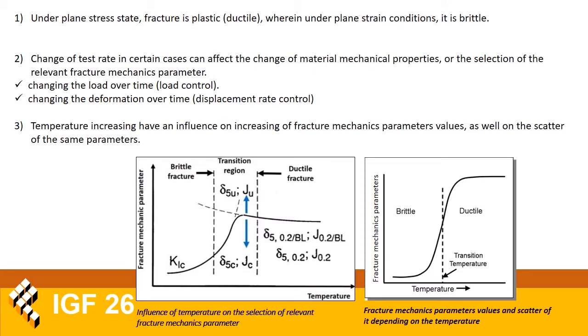As it is well known, plane stress and plane strain state define plastic and brittle fracture. Under plane strain, fracture is brittle. One of the ways of achieving plane strain state in a specimen is to take into account specimen thickness. The larger specimen has an influence that fracture is more likely to be brittle, as reflected on the relevant measured fracture